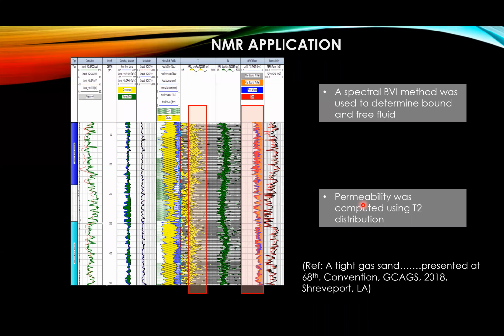And then we derive a permeability. If you remember, I said that when you have bound water and a lot of small pores, your permeability goes low, and so NMR helps us. When we are considering the permeability, we will consider probably this section here, but not the signals coming from here. This will be more like bound water. Where you put this cutoff depends on your experience, or the experience in a particular area or particular rock type. And then you can compare it, of course, with a core permeability measurement, and fine-tune that to optimize it. So that's how NMR has a big say, or helps, in this kind of rock.